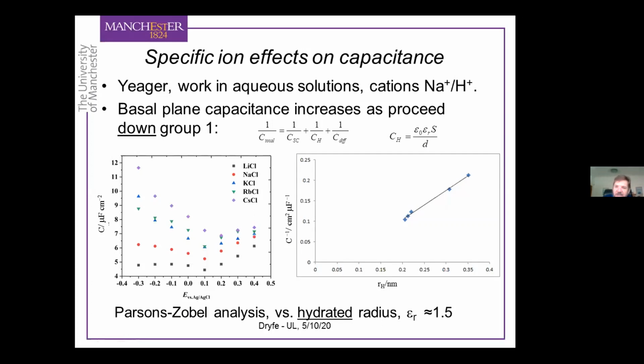And do we get a physically sensible value for the relative permittivity of water in this environment from this very simple plot? And the answer is perhaps, because we get a value of less than 2, which, if you look at the literature in this field, obviously water is constrained, and it's known that the relative permittivity of water on an electrode surface is low. And the most recent values have suggested that the relative permittivity of water on a graphene surface at least could be as low as 2. So even though it's a very simple analysis, we're getting numbers that are perhaps consistent with more sophisticated analysis that people have done of the graphite, or graphene in that case, water interface.